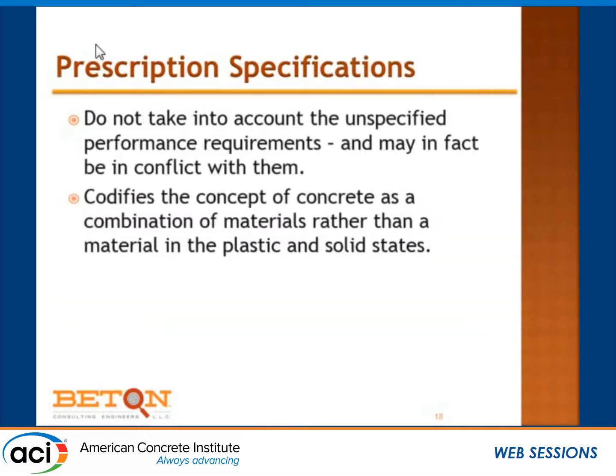And some of the issues we run into with the prescriptive elements are the ones that we should try to avoid as engineers. They don't take into account the unspecified performance requirements, and in fact, they may conflict with them. And I'll give you a couple of examples. But worse, it codifies this concept that concrete is a combination of material where both hardened and plastic concrete are composites. If you specify the nature of a resin and the nature of a glass, and then you make a fiberglass, you may find that what happens is the interface between the glass and the resin controls.